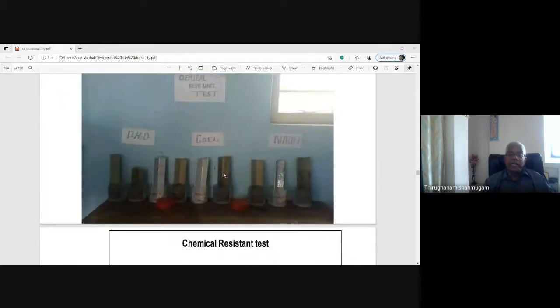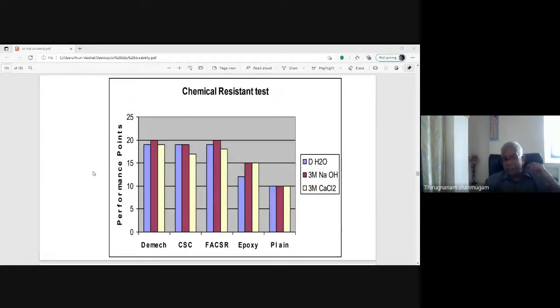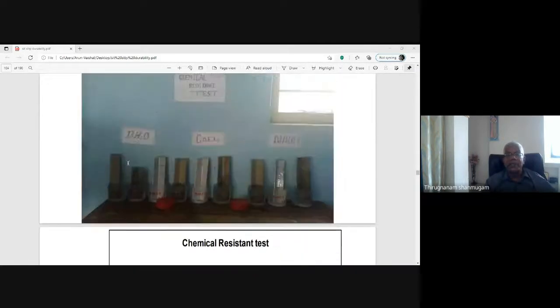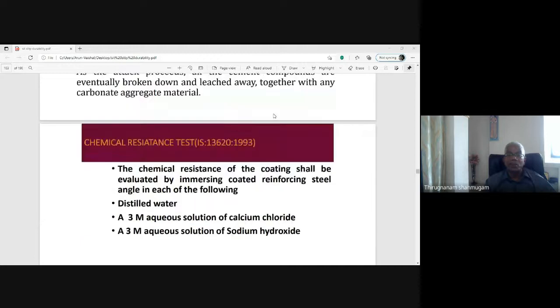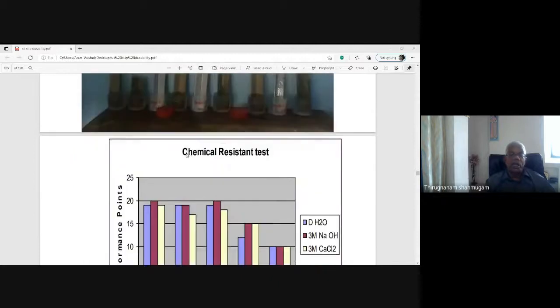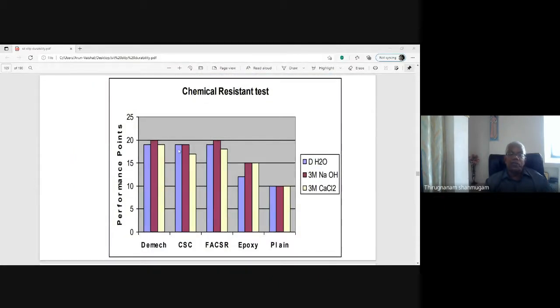So these are the coated angles, these are immersed in the solution. And the result is the performance index point calculated according to the codal practice IS 13620:1993 code. Performance points are calculated. You can plot that. The plain uncoated angles have only a 10 performance index, whereas the Demech coating is up to 20% against 3 molar sodium hydroxide solution and like that.